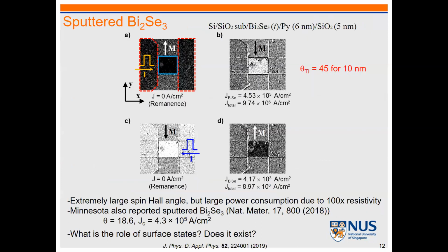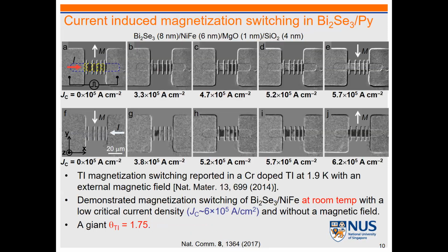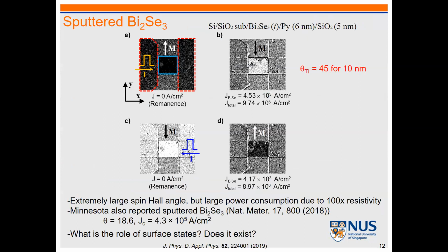Then one of the criticisms was that we grew this bismuth selenide using molecular beam epitaxy. Of course, it's not really an industry-friendly technique. So then we tried to grow this with sputtering. We just bought the sputtering target and then grew bismuth selenide and permalloy, and you can do the same thing. This is a microscope image from the top view. You can see black to white domain, white to black domain with much smaller current density. The spin Hall angle in this case is estimated to be 45.